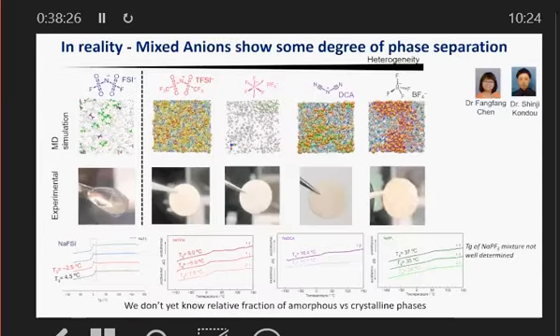But when we actually made the materials, unfortunately, we got increased heterogeneity in these systems. So in reality, this corresponded to phase separation. But the phase separation is not necessarily, again, the salt crashing out, because we still measure DSC. We measure Tg of these systems. The Tg of the BF4 is significantly higher than the other systems. It might mean, are we measuring Tg of just the regions here, which is amorphous? Are we measuring the interfacial regions between the solid, the crystal, and the polymer?